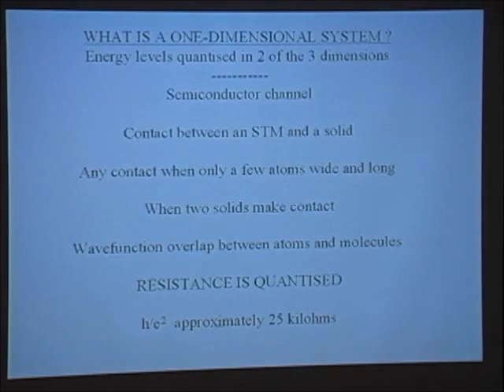Now, the interesting feature of this, which makes it completely different to macroscopic behavior, is that the resistance, if we measure a resistance, is quantized. And it's quantized in units of the fundamental constant of conductance, which is h over e squared, where h is Planck's constant and e is the electron charge. It always comes as a surprise to realize that that actually has dimensions of ohms. But it does. A 1-dimensional system in which there is no scattering, where transport is ballistic, has a resistance which is just over 25 kiloohms.